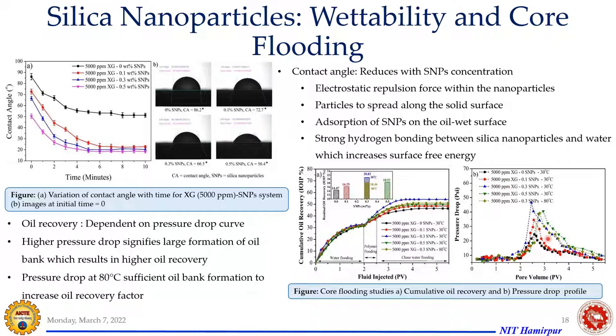And there is a pressure drop curve on the right-hand side. You can see that initially at 0 nanoparticle concentration, the pressure drop is increasing and then it goes back to the same level. But as we keep on increasing the nanoparticles, you can see the pressure drop curve is increasing, and at 0.3 we get a high pressure drop. This indicates that there is a formation of an oil bank, because of which a huge pressure drop is encountered during the flooding experiment.